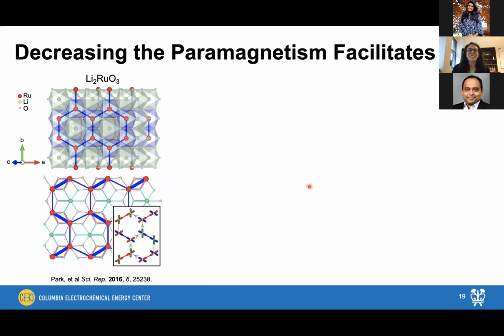So the first thing that we ended up studying was the CEI that's appended to the lithium ruthenate structures. And we were interested in these ruthenates because they have these ruthenium dimers in them that actually serve to quench one of the paramagnetic sites of ruthenium in this structure.